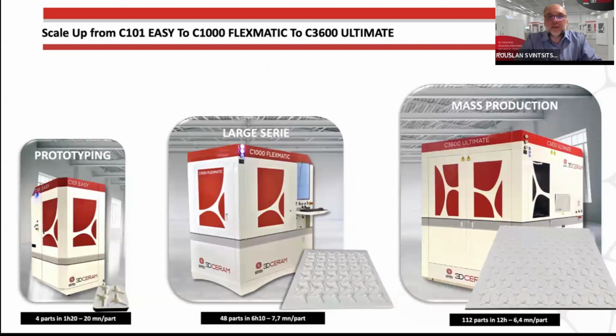So what is the economic reason to go from the small machine to the big one? It's simple, because of the big plate. When you take one typical part, a kind of spider part, you can see on the plate pictures under each machine that in the first case, for prototyping, you can print 4 of these parts in 1 hour 20 minutes on the small machine, 48 of these parts in 6 hours on the mid-sized machine, and 112 parts in 12 hours on the bigger one. So you can see that the time per part is really in relation with the big plate. You can print much faster with a big machine.